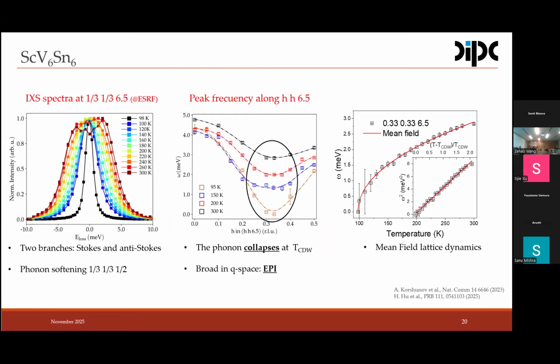But as I said before, the diffuse scattering is an energy integrated experiment. All the energy comes to the detector. If we want to resolve what part of this diffuse signal is actually elastic and what comes from inelastic, as inferred from the momentum dependence of the diffuse signal, we go to inelastic X-ray scattering. We put the sample in the beam, and we can record the inelastic spectrum. At high temperature, in this brown scan, we see a Stokes and anti-Stokes branch, low energy phonons with more or less 4 to 5 millielectron volts at high temperature.